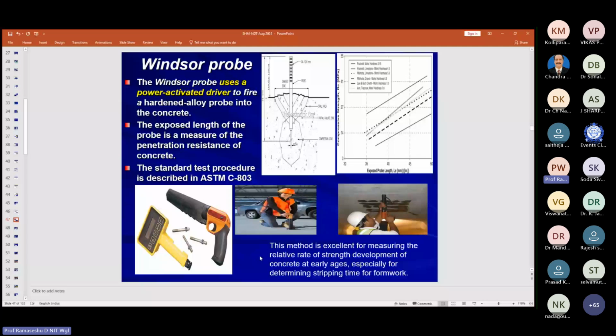For example, you cast a cube, let us say, and try to use this Windsor probe test on this cube at different days of curing. Let us say 3 days of curing and 7 days of curing. Let us say 15 days of curing, 14 days, 21 days, like that. As the number of days increases, the probe penetrates less into the system. That means as the concrete is getting stronger, gaining strength, it doesn't allow this probe to penetrate. Okay. It's a very useful instrument.